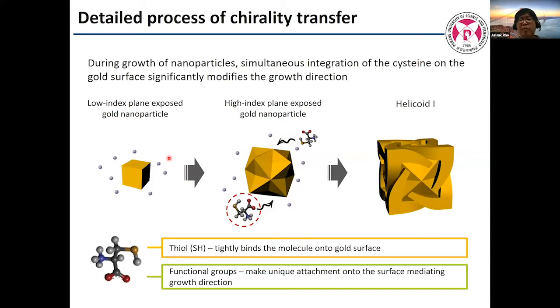It was really interesting. But why didn't people know before? So the problem is here. This is cysteine, one type of amino acid, and when the amino acid is exposed to such a gold nanoparticle, they don't do any reaction. Although the thiol is like gold, there is no interaction between the two. But if we use a little more complex structure, this is called the hexoctahedron, having high Miller index planes of 321, now these start to interact with the gold nanoparticle.